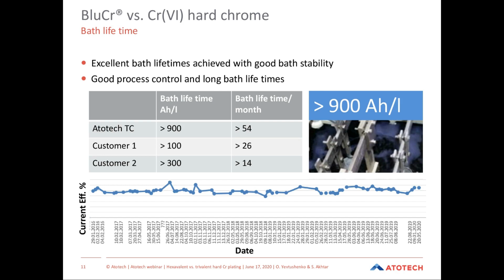In terms of the bath life of BluCr electrolyte, this is quite long, and to date we have operated a bath in our automatic pilot line to 900 ampere hours per liter over a 54-month period. So we don't see any issues related to bath age whilst we have been operating this bath. And at two of our customers, we've achieved between 100 and 300 ampere hours per liter.